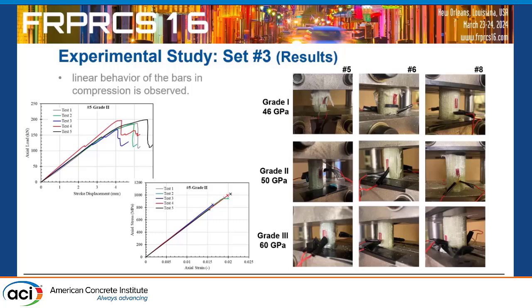So this is the big picture of one sample for each case, number 5, number 6, number 8, grade 1 to 3. And for the majority of cases, we were able to have the failure in the gauge length. We had a few that happened inside as well. Here is the typical load versus stroke. These little things are a little bit of slip.